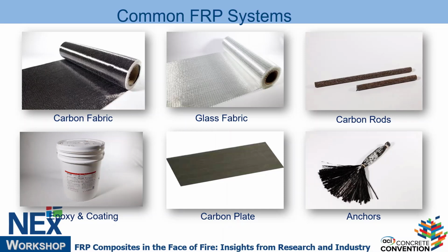It consists of fiber that is woven into fabric or just loose fiber that comes in. You can use carbon, glass. There's basalt fiber. There's aramid fiber. But these are the most popular for structural applications. These are mixed with epoxies where you saturate them on site and then glue them to the surface to create this basically cured-in-place, high strength polymer, very durable, that increases the capacity, right?